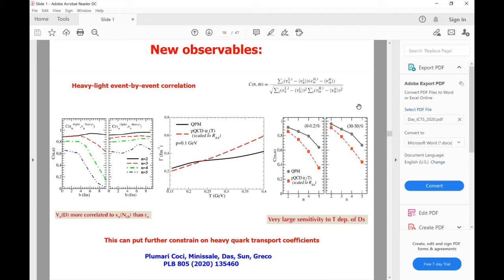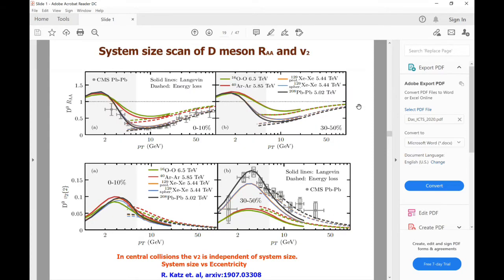Meanwhile, the system size scan is also another interesting issue, because this will provide us a hint about the origin of v2 in small systems. As we can see, they have studied R_AA and v2 for different systems. In the case of R_AA, as we reduce the system size, the suppression decreases for both centralities. But if we look at the v2, it is almost independent of the system size. No matter which system it is, the v2 is almost constant. This is because there is a competition between system size and eccentricity. For a smaller system, the eccentricity is large, which compensates for the small size. At the end of the day, the v2 is almost similar. So if this is observed experimentally, certainly it will help to understand the origin of v2 in small systems.